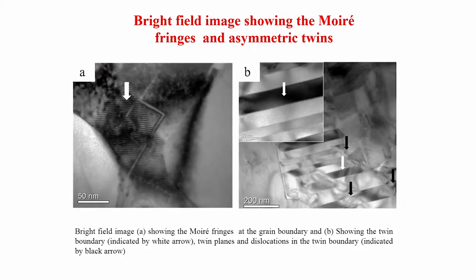Another bright field image shows moiré fringes as well as asymmetric twins. These asymmetric twins essentially indicate that when these materials are heated at high temperature under uniaxial compaction, deformation twins are generated, particularly at high temperature, and they remain when cooled. These twins are present across the grains, because once a twin starts it does not terminate in the middle of a grain unless intersected by another advancing twin — the same phenomena we learn in standard materials science textbooks and observe also in ceramics.